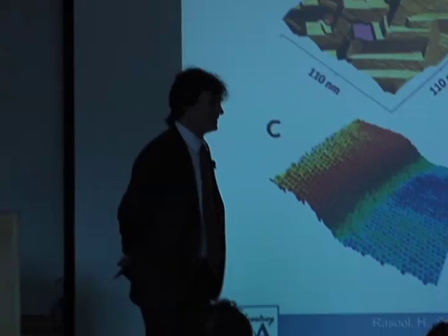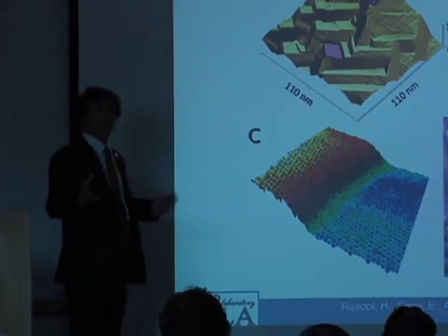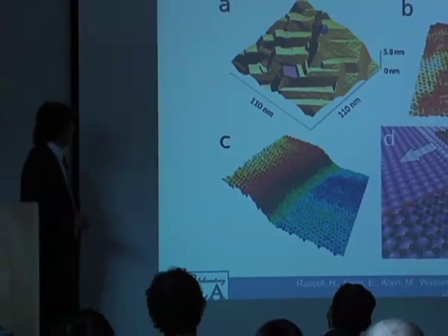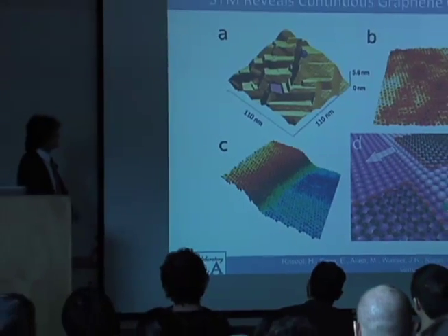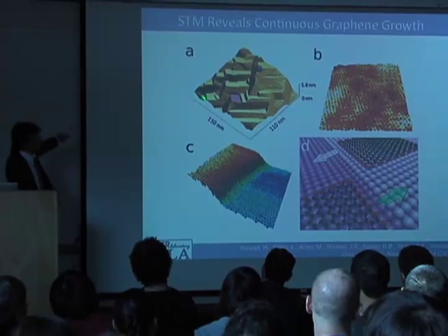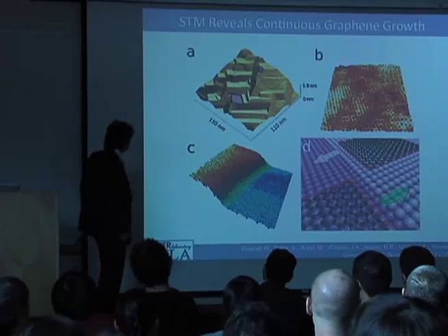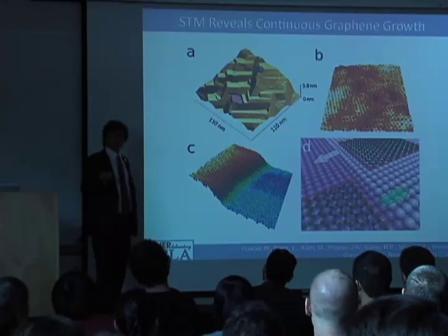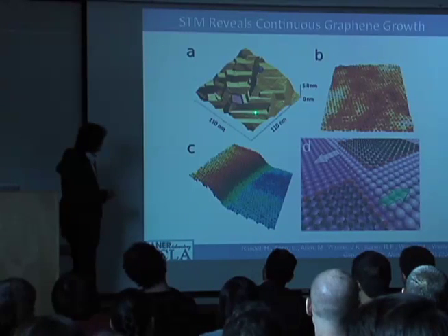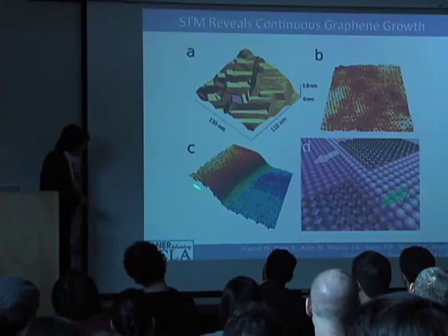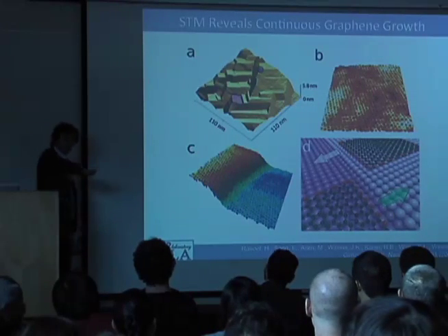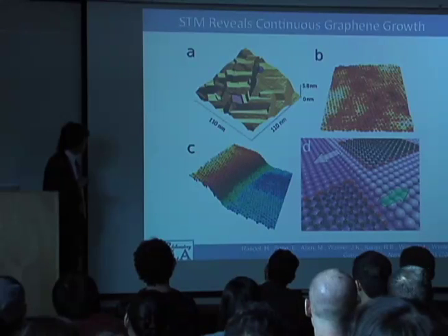Now, one of my colleagues, Jim Gimzewski, is an expert in scanning tunneling microscopy. And so we were interested in what's going on with this copper surface if you try to grow graphene. And copper is a nice crystalline inorganic solid. So if you look at this STM map, you'll see all the hills and valleys and plateaus. Nice crystalline material. So what happens when you try to grow graphene on this? It nucleates someplace. And here's an STM map of the carbon. It grows right over one of those hills and valleys. So basically, it nucleates and just grows independently of the material.